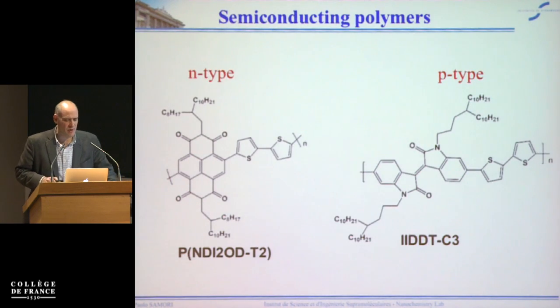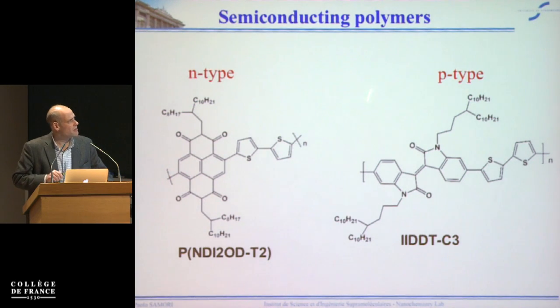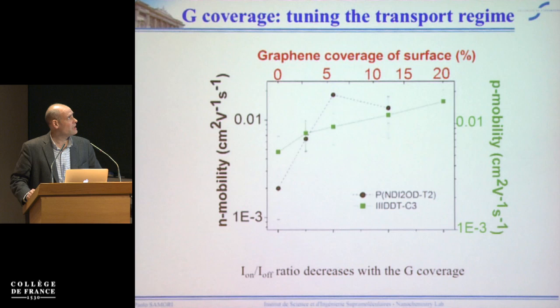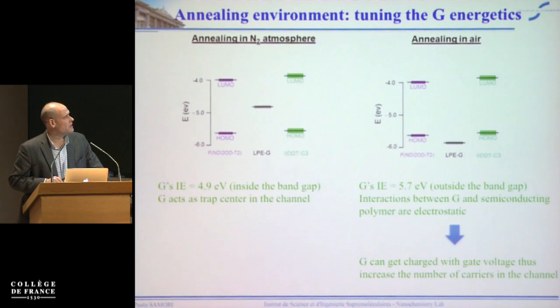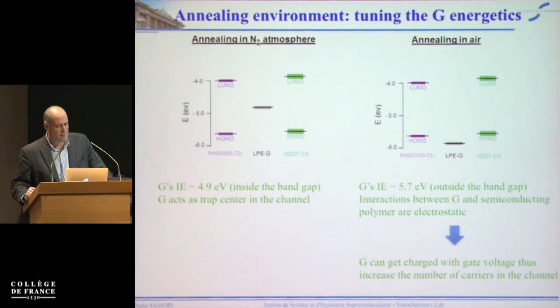The polymers we decide to play with are the following. These are both commercial polymers, N-type and P-type. Now, the more you increase the graphene coverage on the surface, of course, the more charges pass through the graphene flakes, and so you have an increase in the mobility, both in N mobility when you play with an N-type polymer, or P-type mobility when you play with a P-type polymer. And now the major problem is that the on-off ratio is still not terrific. We will see more precisely in a few slides why.